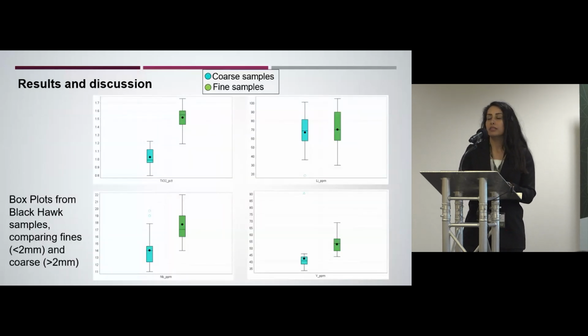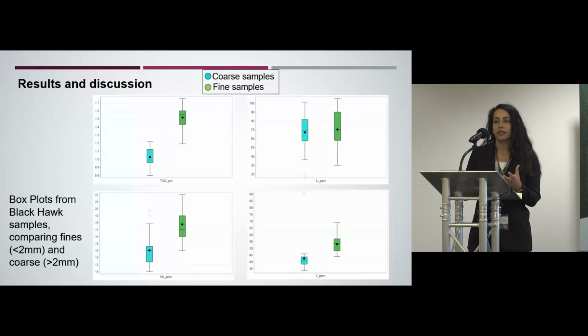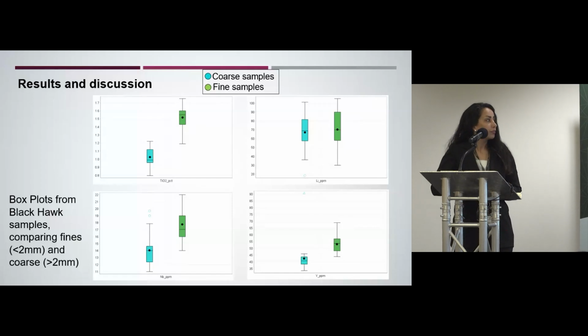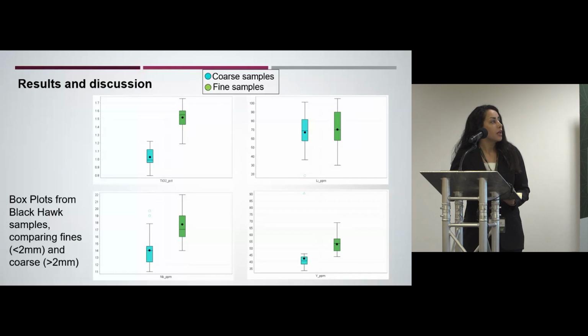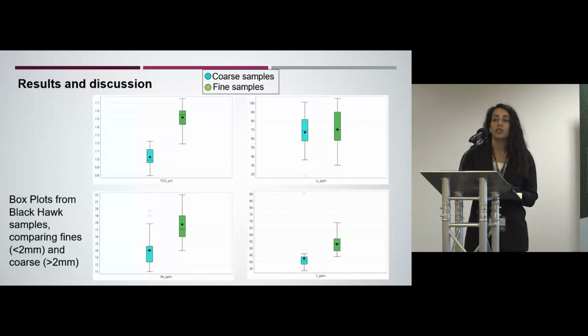For the Black Hawk samples, we separated the samples as fines and coarses by sieving them to compare the different concentrations that we had in our fine and coarse samples. As you see, these box plots show the variability and the average of those concentrations in fines and coarses. For example, for lithium, there isn't a big difference between the concentrations in fines and coarses, but regarding the titanium oxide, niobium, and yttrium, our samples were much more elevated in fine samples rather than the coarse.